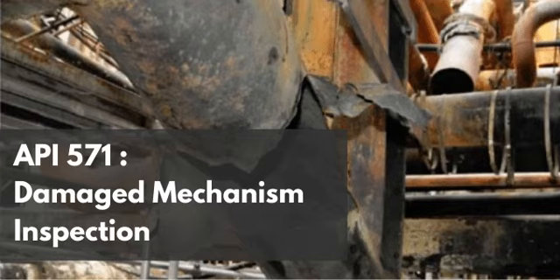You must ensure the welding consumables, the filler wire chemistry, and the welding heat input procedures are designed to keep the final ferrite content at or below that roughly 10% threshold mentioned in the text. So an inspector on a fabrication floor has to be constantly checking the ferrite number of the welds as they're being made. Yes, constantly. It's all about balancing the risks.